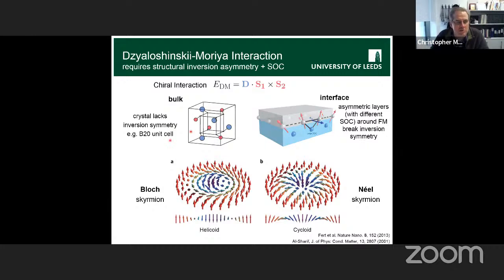And the first Skyrmion materials, like that iron cobalt silicon that we saw before, this was done at the level of the lattice. So here's a unit cell of this B20 lattice that those materials have. And you can see it has a rock salt structure, but it's been twisted. Every atom's been displaced a little bit from the corners of this cube. So you have a cubic unit cell, but the basis inside the unit cell has a twist, has a handedness, and it lacks inversion symmetry. And that gives rise to this DMI.